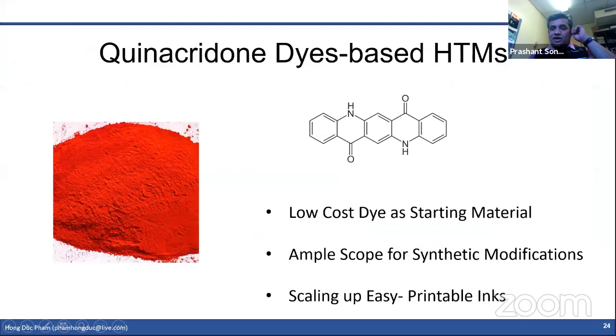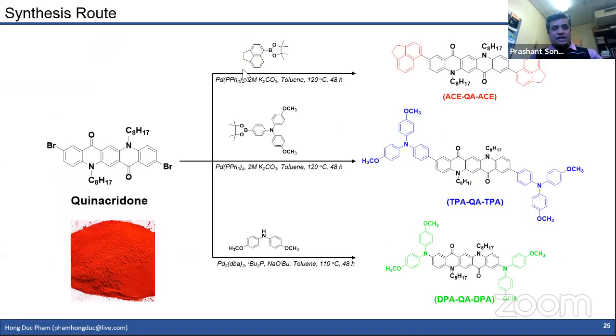So we picked up another dye, which is a quinacridone dye. And this quinacridone dye again has a ketonic group and alkyl group, which we can utilize as a solution processable motif, like an octyl group. And then again, taking this end capping group, exactly the same, only we changed the dye here. We took a quinacridone. In the earlier case, we had anthanthrone.